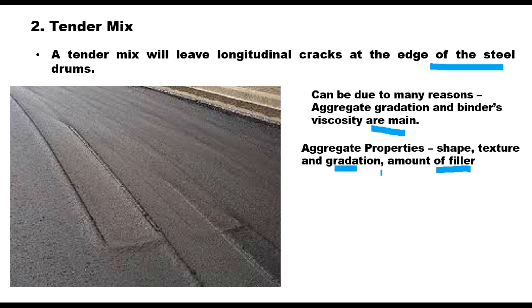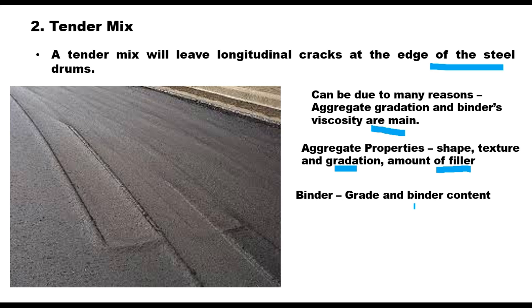It is important to keep the filler-binder ratio in the range of 0.6 to 1.2, and try not to blend the aggregate too close to the lower limit of the gradation range. Binder grade and binder content are also important. Selection of a stiffer binder can help reduce tenderness. Similarly, too much binder in a mix contributes to excessive fluidity, causing the aggregate to float around. Low shear strength and low friction are by-products of high binder content.